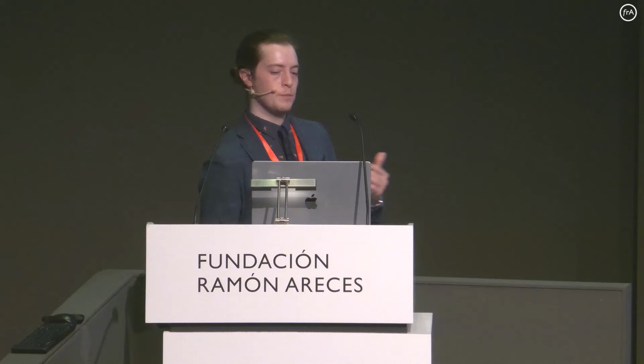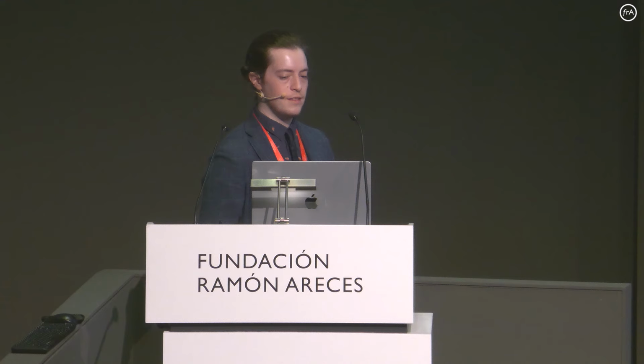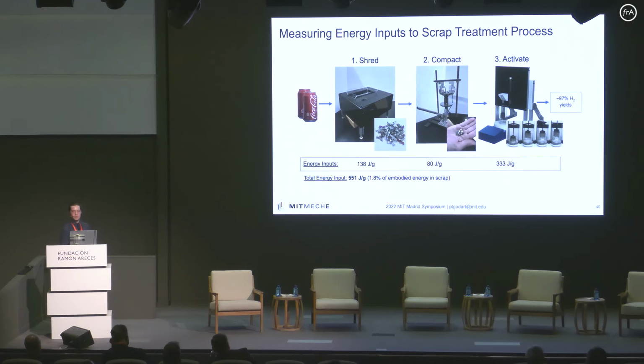I then went ahead and measured the energy inputs to this process and showed that even in a very conservative, very inefficient lab setting, we can still do this treatment process for less than 2% of the energy that we get back out from the aluminum. And again, that's because all of that energy that's embodied in the aluminum went in during the reduction process. And here we're just manipulating the aluminum in a pretty superficial way, actually, to make it water reactive.